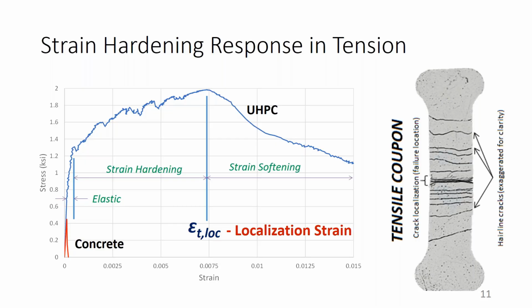you can see concrete at the bottom left, all the way down here. You can see that once it cracks, it loses all ability to support load and drops right away. But UHPC is different. Basically, the first crack forms. The fibers say, no, I'm not gonna allow you to fail, and they bridge it. And then another crack happens, and a third, and a fourth, and a 20th crack. And when this happens, we call this behavior strain hardening, or the multiple cracking phase. The material does not fail upon first cracking.